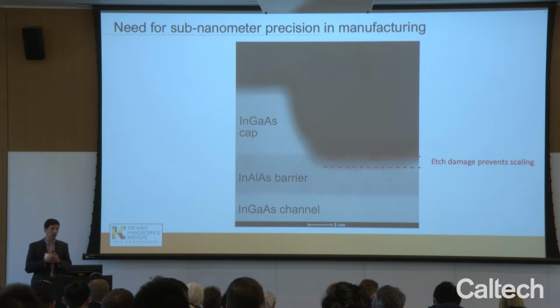This type of etch damage, you can see from the length scale, is on the order of 10 to 20 angstroms, which is exactly the length scale that we're saying we need to pattern these devices with very fine critical dimensions. So this fuzzy region that you see here is the challenge for scaling. In this particular device, it limits the vertical scaling, which then essentially limits the high-frequency performance of the device and hence communication speed. And in logic, there are associated limitations on the speed of the transistor.